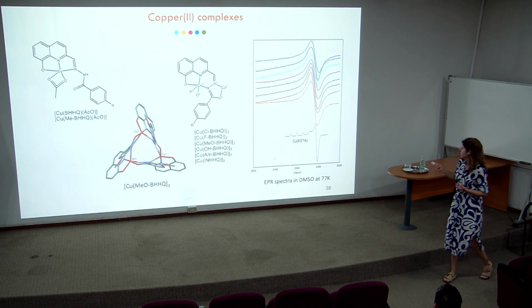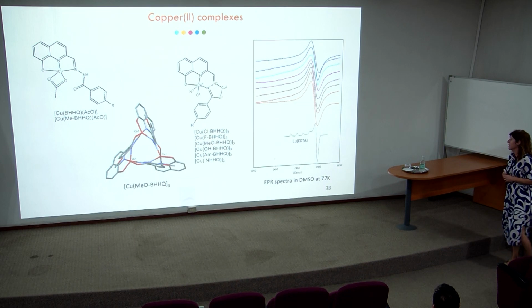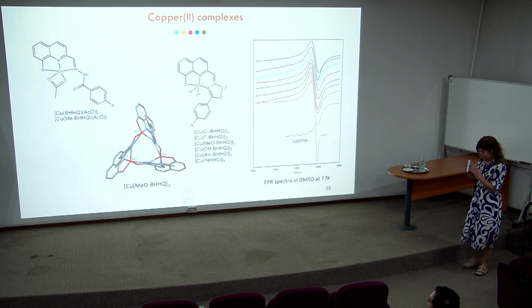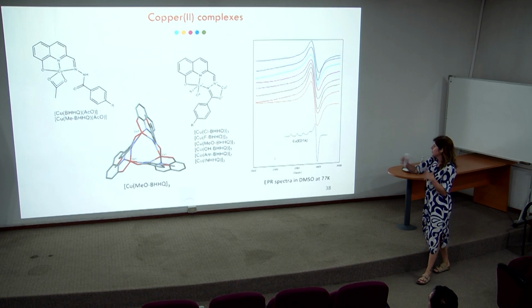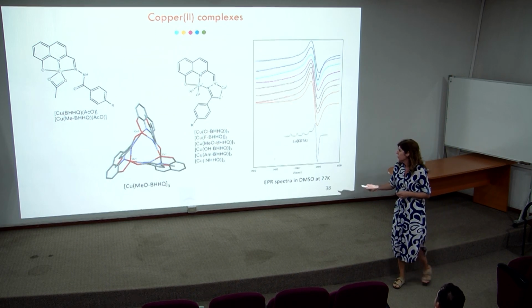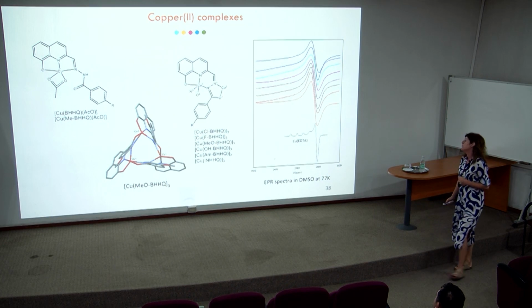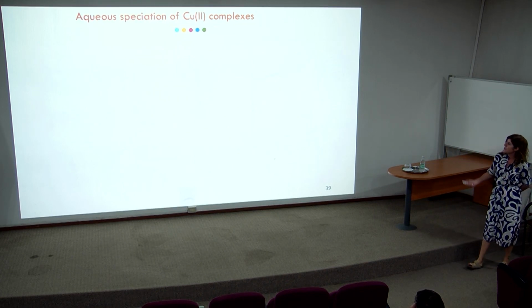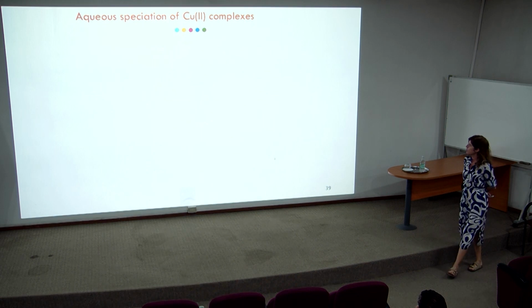I show you here, for instance, the copper EPR spectra in the DMSO, and they have no resolution. They are typical of species which are interacting with each other. So we study this process by magnetic properties. And of course, we did the aqueous speciation of the copper complexes.